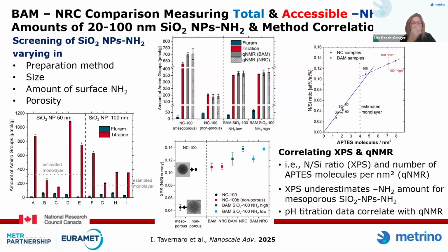So when you take a look now into the data here in the silica particles comparing the Fluram assay and the titration, you naturally see the numbers differ. They must differ because you use protons, which are ultra small, grab every functional group on the surface, every amine functionality, whereas the Fluram assay cannot bind to every functional group. The dye is too large. So this gives you an idea about why it's important to know, do you measure total or a number of derivatizable, conjugatable groups?